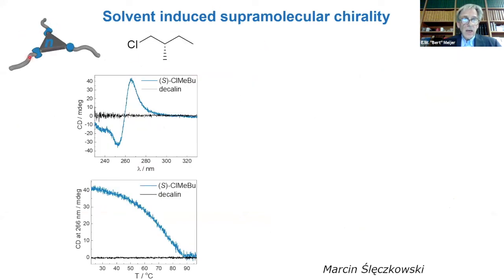Then we took the achiral molecule with a chiral solvent. And what you see is that, without specific interactions, this chiral solvent makes that achiral molecule form one helical form only. Actually, the optical activity at room temperature is exactly the same as that of the chiral molecule. So the role of the solvent is as strong as a stereocenter in the molecule.